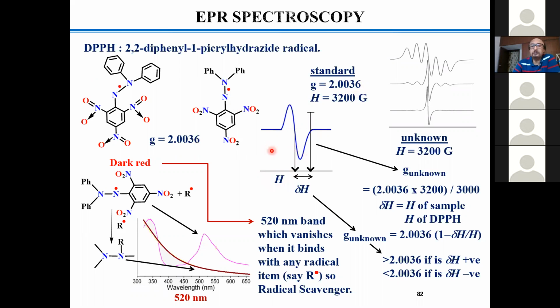Now once you get a spectrum like this, an isotropic spectrum that looks like a radical, it may not be a radical. If you calculate the g, you may be getting 2.001. Once you get 2.00 something, that means that is a radical, whatever the profile looks like. But if it is 2.09, if it is 2.07, that means that is not a radical. You must have a metal complex where the electron is partially distributed at the interface of metal and ligand. It is shuttling between these two, mostly at the ligand, with a partial contribution at the metal site also.